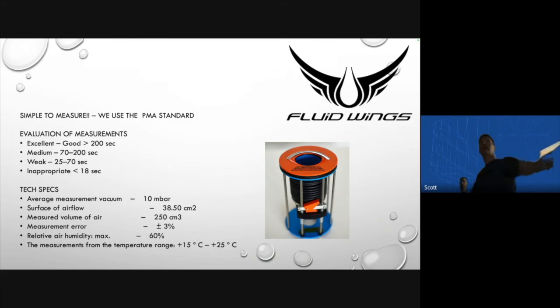We use the PMA standard, so if you get porosity feedback from us, it's been tested on this particular device, and the tech specs are all the same. They're done under 10 millibars. The surface area is 38.5 centimeters squared. This is all metric because it's European. The volume is 250 centimeters cubed, and it's done at a set humidity and temperature, and you just draw that volume of air through the fabric, and the time it takes is your permeability.